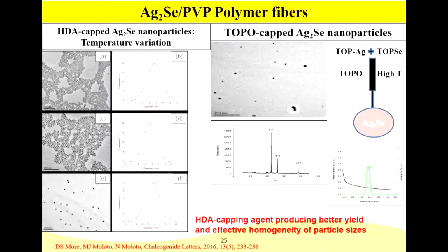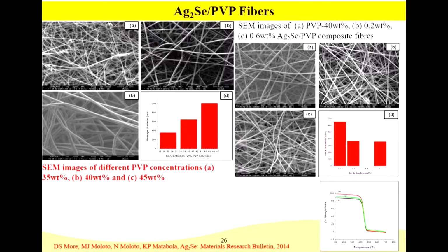Silver selenide was also being incorporated into the polymers, but before you do that, we prepared it by using different capping molecules. HDA is being reported, as we've talked about earlier, and also what you call trioctyl phosphine oxide. You can see that indeed for HDA, you've got better control and better formation of particles compared to what you have for TOPO. And therefore, we continued with the HDA capped nanoparticles and incorporated them, even though we know that HDA is not soluble and maybe not biologically friendly. We just wanted to observe, in terms of its stabilized nanoparticles, whether they can disperse nicely into the fibers.